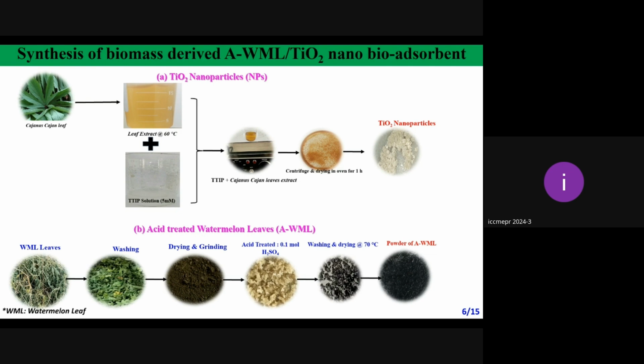And for AWML, which is acid-treated watermelon leaf: after harvesting of the fruits, watermelon leaf is generated in huge quantity and it has no economical value, so it can be used as adsorbent material. To prepare AWML, these leaves are collected, washed, and dried. They are treated with H2SO4 acid, then again washed and dried at 70 degrees Celsius, and we get the AWML powder. When this TiO2 nanoparticle is mixed with AWML, we get the AWML-TiO2 nanoadsorbent.